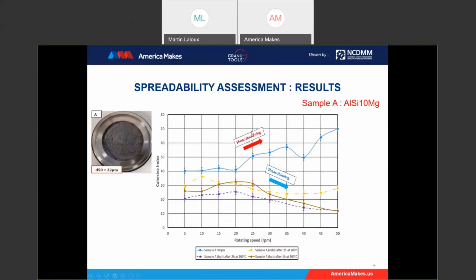When we look at the results, sample A shows different behavior for the virgin powder and the processed powder. The virgin sample has a probability to form agglomerates due to its fine particles, but with heat treatment a shift in behavior happens: no humidity, and the chance to agglomerate is negligible for the hot one. Here you can differentiate the first curve: the blue one is the virgin powder. We observe a shear thickening behavior when you increase the speed. You have the cohesive index on the y-axis and the rotating speed on the x-axis. So the virgin powder will have a tendency to agglomerate, and it will be difficult to spread at high speed.